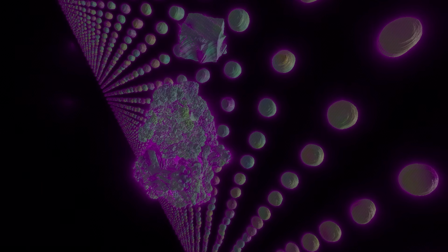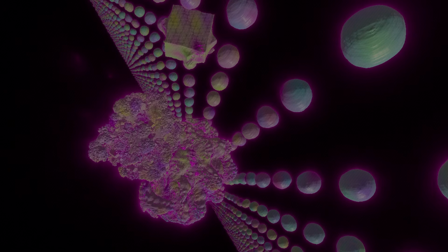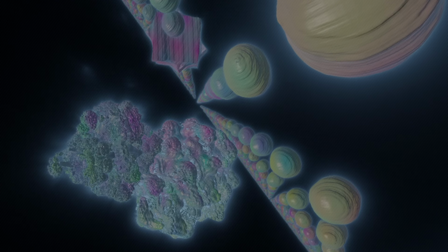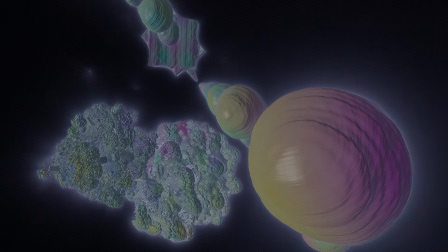And they pair up. Exactly. They form Cooper pairs. These pairs behave like bosons and can condense into a single coherent quantum state where they flow without any resistance. That's the essence of the Bardeen-Cooper-Schrieffer BCS theory. The definitive proof that phonons were involved was the isotope effect. Changing the mass of the ions in the lattice, by using different isotopes, changed the superconducting transition temperature, Tc, in exactly the way predicted if lattice vibrations were mediating the pairing. Later, Eliashberg theory refined this for stronger coupling.